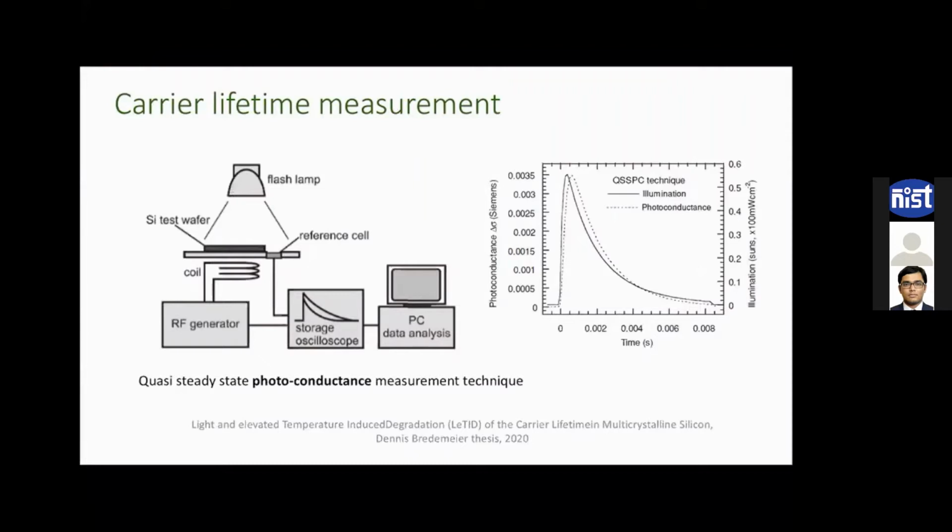Now, how to measure that? Broadly, you can look at some literature on that. You can set up some kind of pulsed lamp system where you switch the light on and off, and you measure the decay rate. For a few monolayers, the rate of decay should not be constant across your whole time scale. You might have two or three lifetimes across your decay time.